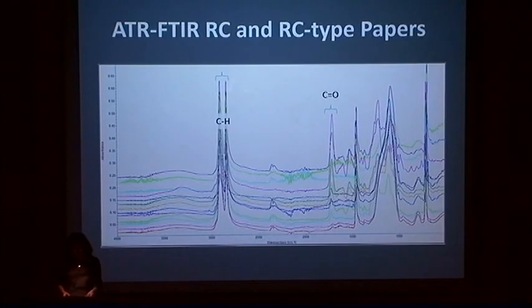We did ATR FTIR on our RC paper samples, and by inspecting the carbonyl region, we can see that not all RC papers are pure unoxidized polyolefins. The FTIR of these 13 papers suggests only a few are pure polyethylene, while some must contain components or oxidized polyethylene due to the presence of carbonyl, or carbon double bonded to oxygen. It is interesting to know that the two bottom spectra